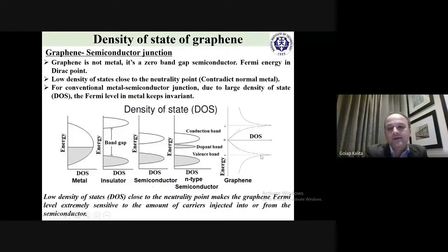But in the case of graphene, as I discussed, due to linear dispersion you have a zero band gap, and at the Fermi energy there is no electron at all, zero electrons. But in the case of metal, you have lots of electrons. So it's totally different for graphene and metals. In graphene, you have no electron at the Fermi energy. Of course, if the graphene is doped p-type or n-type, then the Fermi energy will shift. So that is an interesting prospect: if we integrate graphene with silicon, what will happen?